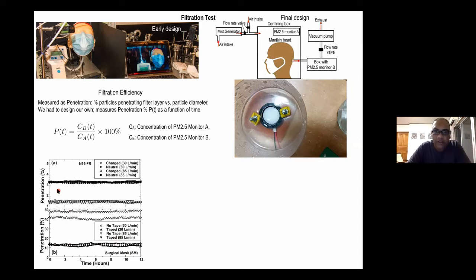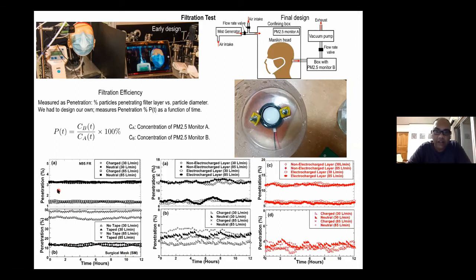Now, let me show you the results from the two designs that I mentioned earlier. The two middle plots are for polypropylene material. The right side plot in red is for the polypropylene polystyrene mix. The top one in the middle is for the surgical mask, where I removed the electrocharge on one of these layers using a static eliminator and made the measurement with it.